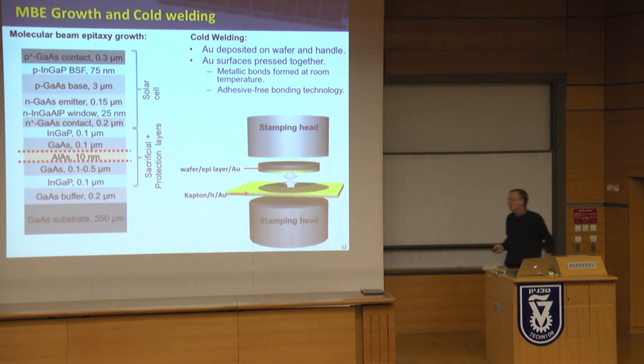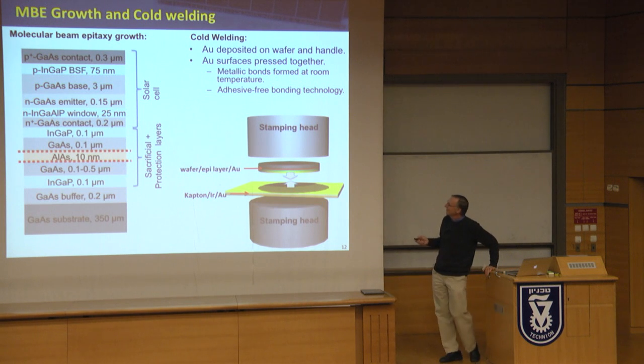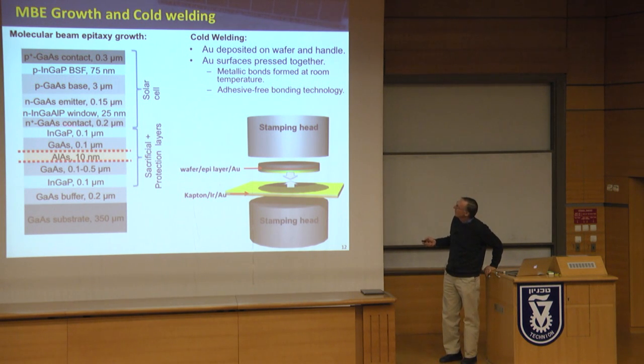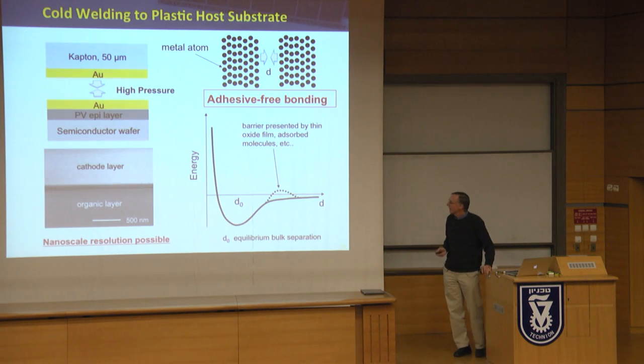This is the structure. It looks pretty complicated, but it isn't, because this from here up is just how you make a solar cell today, a gallium arsenide solar cell. And then this is our world of protection layers. We start with the aluminum arsenide, which is our sacrificial layer, and you'll notice we've got gallium arsenide, indium gallium phosphide, gallium arsenide, indium gallium phosphide down in the substrate. And there's the bonding process again.